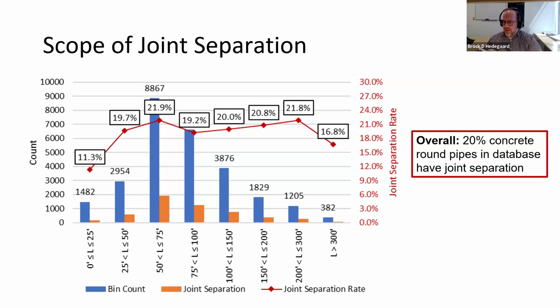So overall, it works out to be about 20% of the concrete pipe inventory that has some form of joint separation. And again, when this gets flagged as joint separation, that means there's an opening in at least one joint that's greater than 1 inch. How long that joint opening has been there is up to debate. We don't necessarily know that. The other thing that we don't necessarily know is if that is actually deleterious to the pipe. In a lot of these cases, many of these pipes with small joint opening would be classified as having separation, but have no issues.